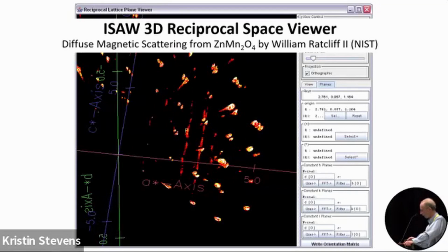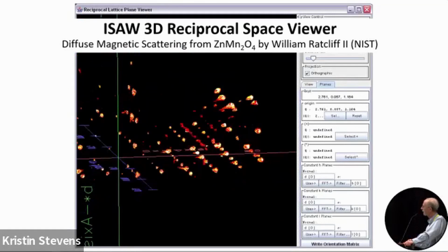And if we step through the data or rotate the 3D data, we see these very clearly, these rods of intensity, and they're due to two-dimensional magnetic ordering at low temperature. But this kind of visualization makes this technique really useful, as you can see.